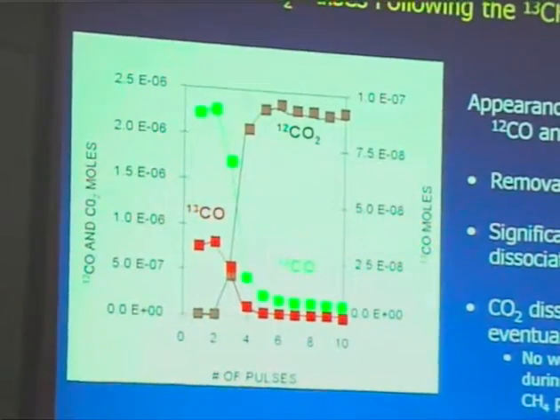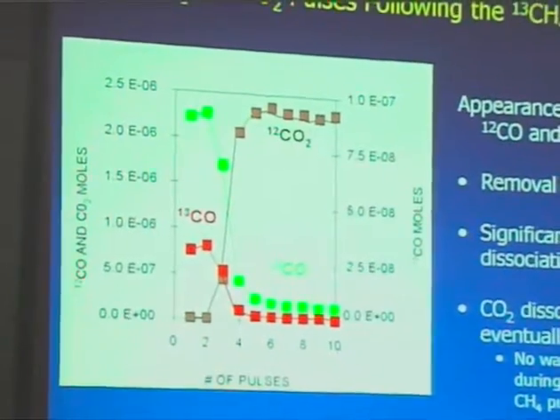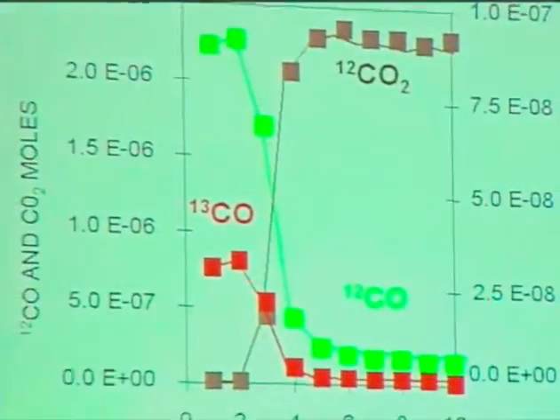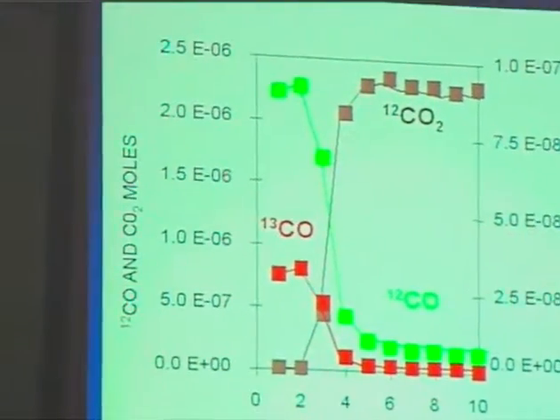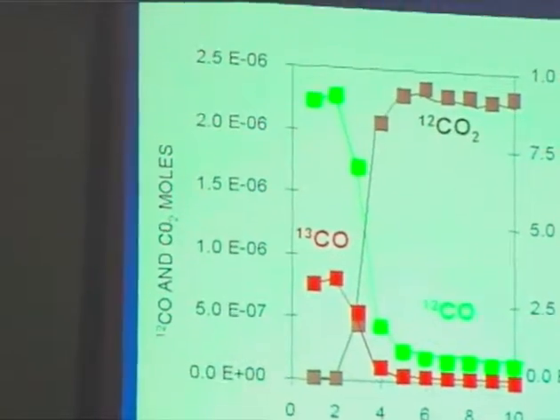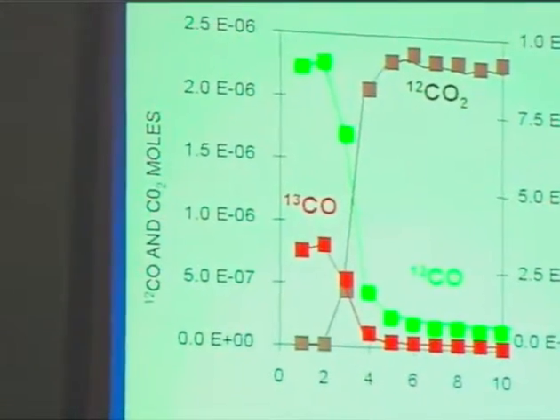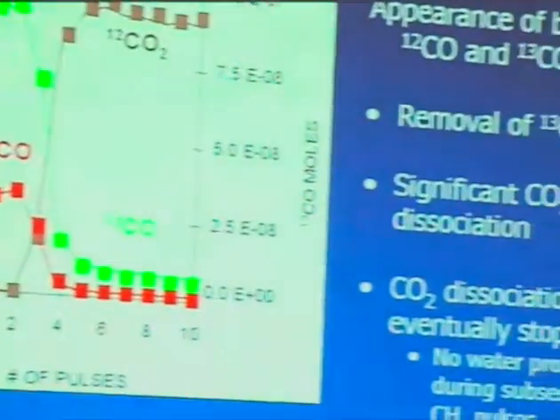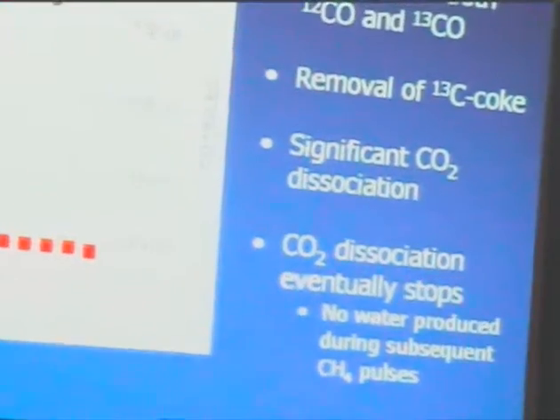We thought that there might be oxidation or partial oxidation of the platinum metal. We've done some studies where we then pulsed methane afterwards, and we do not see the formation of water, which would indicate that there is no surface oxidation of this material. We've also looked at these materials under XAFS, and we don't see any oxidation either.